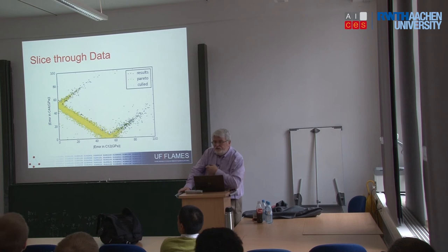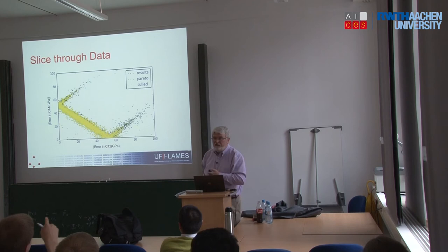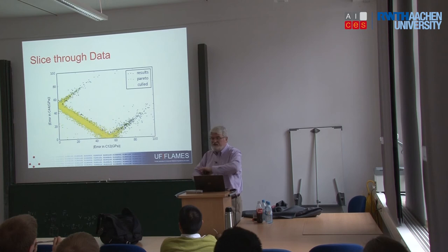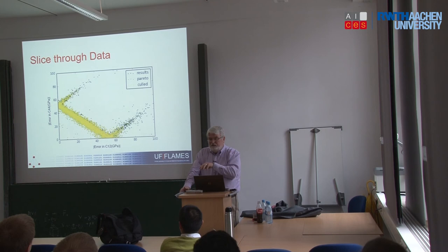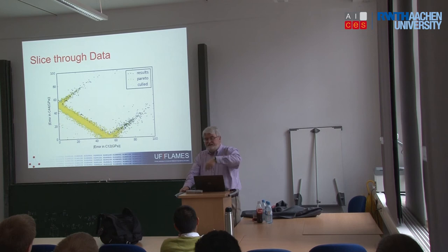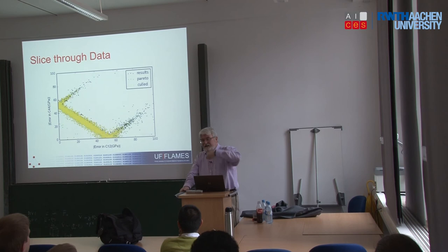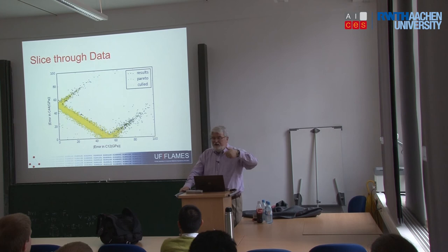Each point is a different parameterization of the potential, a different set of thetas. Yeah, so I start off, I chose 10,000 at random with a uniform distribution in all these parameters. I analyzed those. I found that there was like 900 points on the Pareto front. Then I used the distribution of those values to bias the sampling for the next 10,000. And then they gave another distribution. Yeah, because you go through this process, you keep sampling, it's importance sampling. You're sampling from the places which are most likely to give you points on the Pareto front, and ignoring those points which are far away. You go through this as an iterative process.